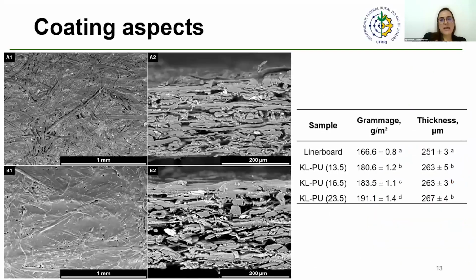So then we applied the formulation to the paper, and to evaluate the coverage of the coating, SEM was carried out, and its image shows good surface coverage and film formation. As we can see here, I don't know if you can see, here we can see the film formation.